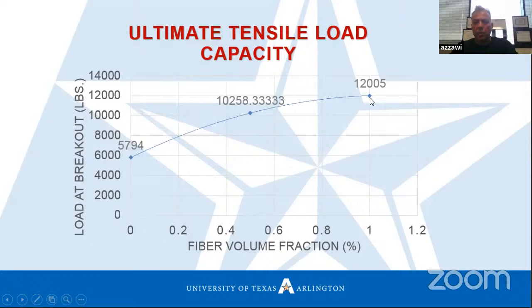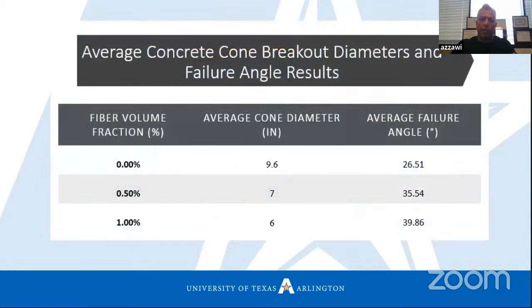So with 1%, the tensile capacity, or we can say the breakout capacity of concrete, is 12,000. With 0.5% it is around 10,000. With 0% it is 5,700 pounds. So just providing some fibers in the concrete mix, especially in pedestals, in the anchor pedestal zone, will improve the ultimate tensile capacity a lot, especially if we have uplift, if we have a windy area, if we have a structural steel building.